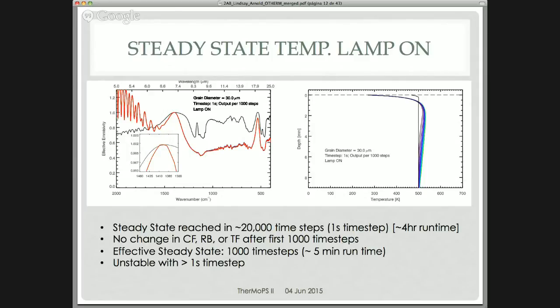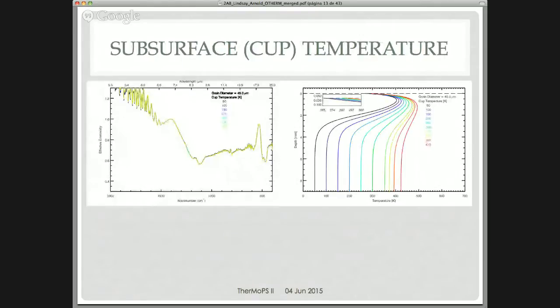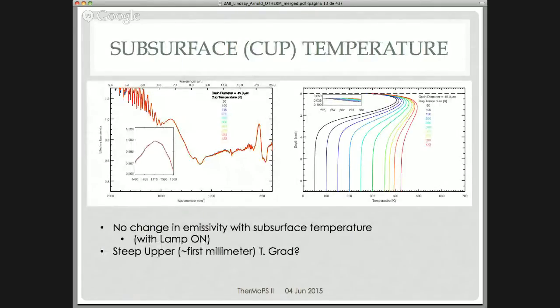And finally, I was very interested in that steep temperature gradient and how that might compare to subsurface temperatures. So here I've just varied the bottom temperature in the code over a wide range, and went ahead and let it evolve to, these ones are about 10,000 time steps. But you can see this steep temperature gradient, and even with a variation of about 30K,